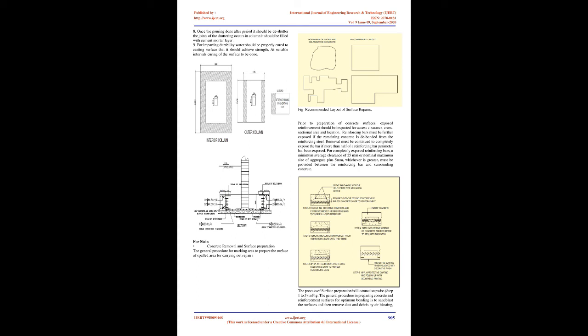4. Foundations. 1. Removal of loose concrete from the members so as to prevent deterioration or debonding issues. All loose particles from the concrete should be removed around 50 to 75 mm from all the sides of the foundation. After removal of loose concrete, the entire surface should be wetted by spraying water. 2. After the removal of the loose mass of concrete for surface preparation, the existing reinforcement is exposed to the atmosphere, which is treated with anti-corrosive treatment to avoid corrosion in the steel.